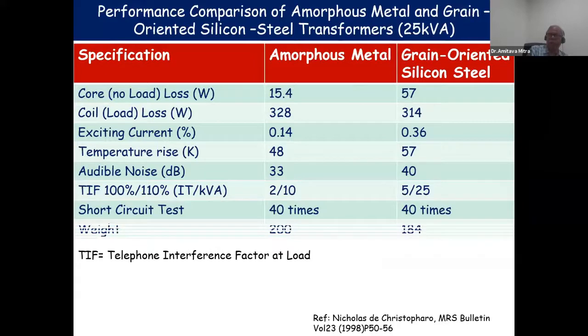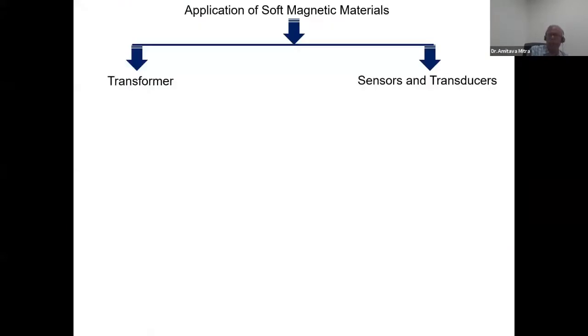And you can just compare this core loss - no load loss is equal to 15.4 watts, and in this case 57. So you can understand how much, but there is a little bit higher load loss because this amorphous alloy has high resistivity. So this load loss is little higher. But if you consider it in totality, it is much more advantageous for the transformer cores.